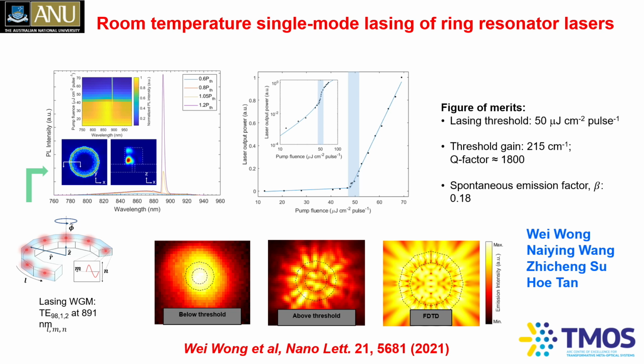Below threshold, you see a broad light emission, acting like a light emitting diode, a spontaneous emission. Above threshold, you see these beautiful whispering gallery modes. You can compare these with theory, and they match very well, indicating again that 3 years of hard work by Wei Wong really paid off. Again, there is threshold-like behavior: below threshold, a broad line width, and above threshold, a narrow line width you would expect from a laser.